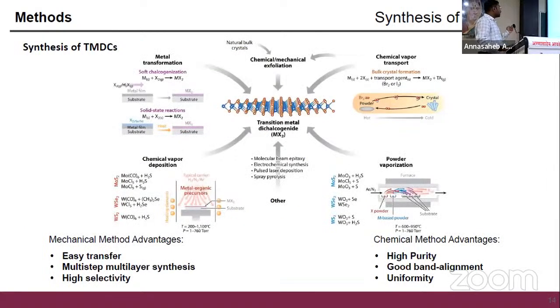So as I talked about, in order to synthesize these 2D materials, there are different ways. So basically in this slide, I am summarizing it. In case you need to synthesize these TMDC materials, there are some metal transformation methods. Then you can oxidize it or sulfurize it. Also the chemical vapor deposition technique which I talked about. Then you can also directly vaporize your powder, and you can make the thin film depending on the thickness you desire. So typically these are the ways which are currently used in order to synthesize this kind of thin film 2D materials, not only TMDCs but others also.